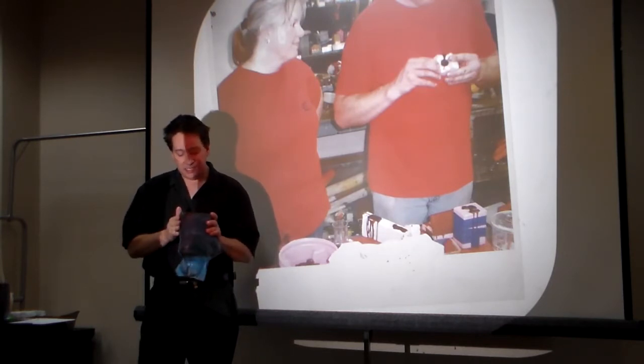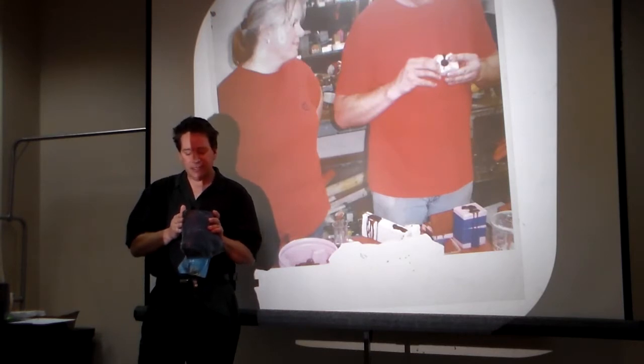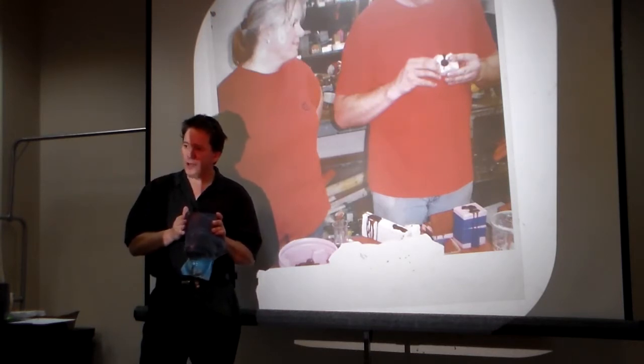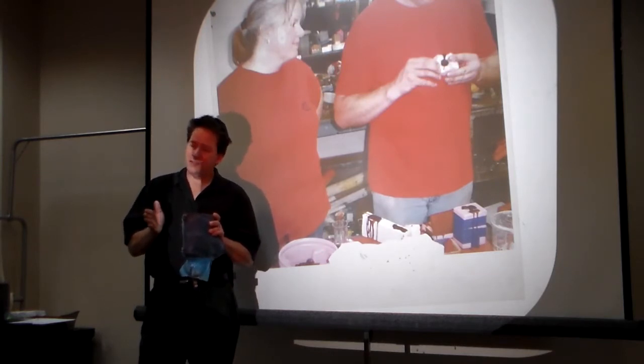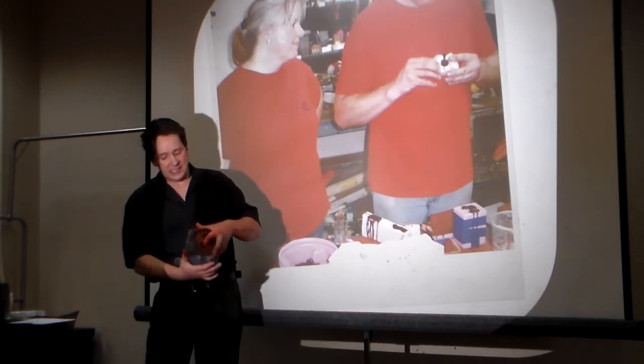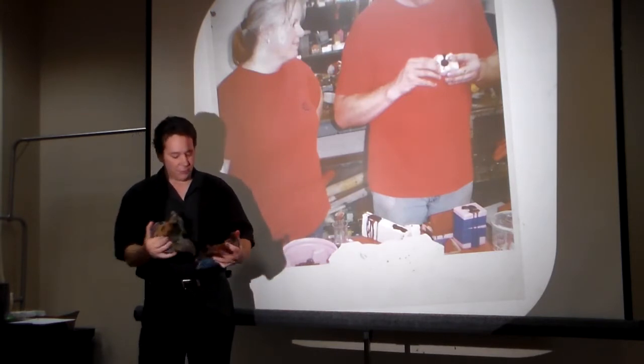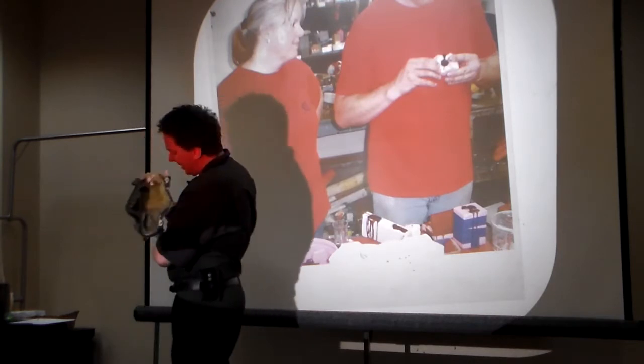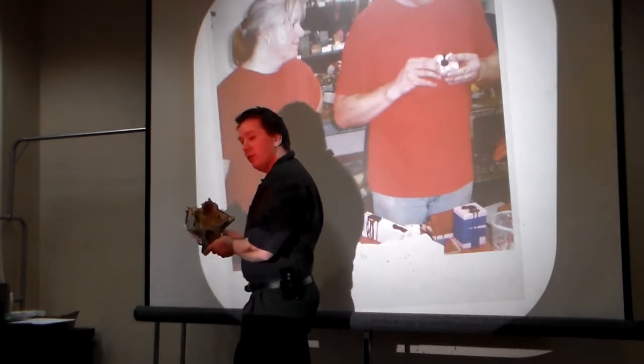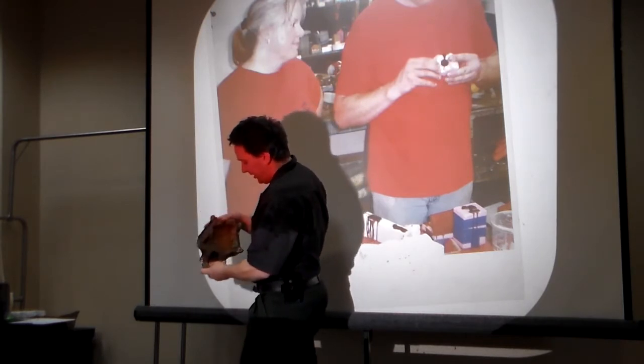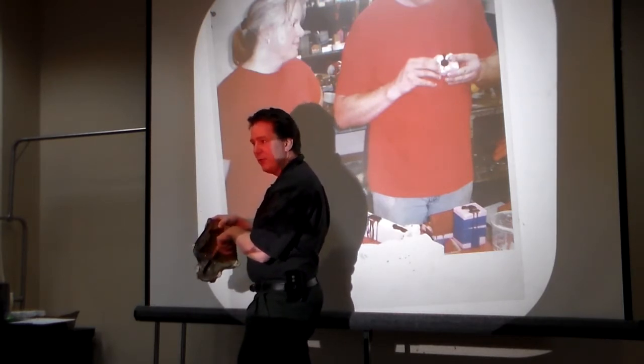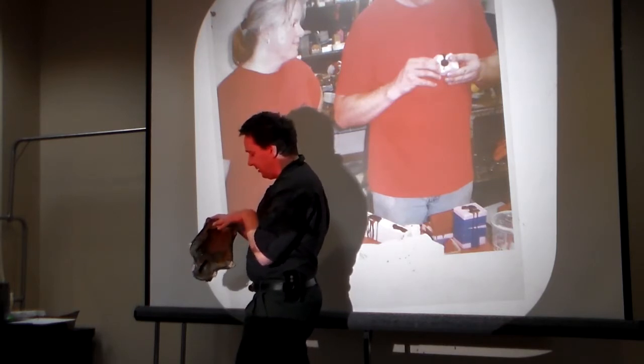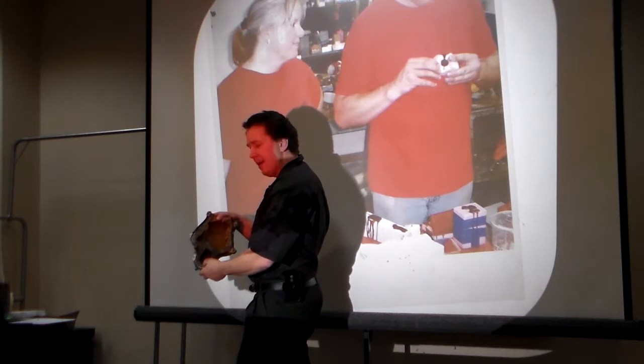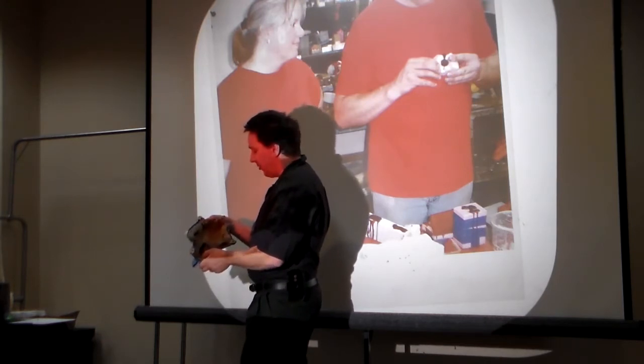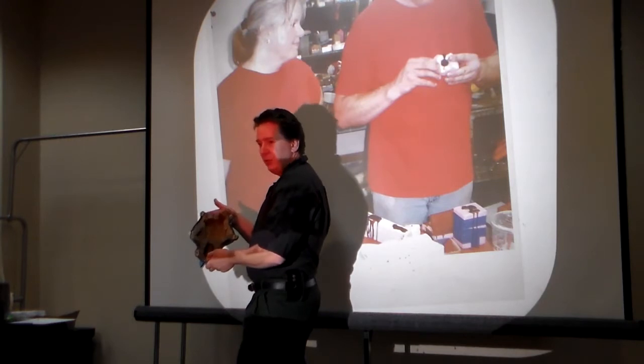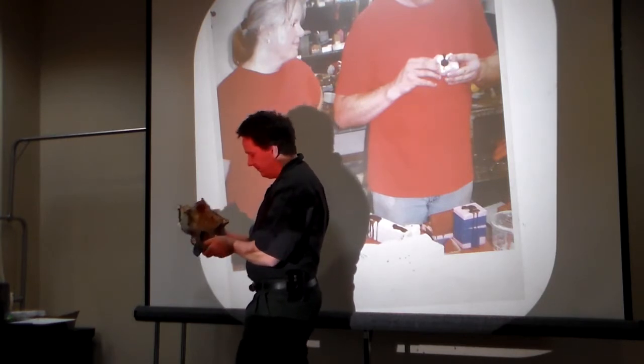Now it's an important detail on making these hollow castings in wax that we control the temperature of the wax. We want it hot, around 105 Celsius for that first one, so any of the details on the surface don't have trapped air. We need a very thin, low viscosity wax for that. The problem with that, if we go into a second and third layer, I'm pouring wax straight down, wherever it hits, it's going to remelt the surface of what I already have cooled in there. So that second pass with wax, I want the temperature about 80 Celsius, and then the third, fourth, and fifth, 70 to 71 Celsius, where it's just barely molten.